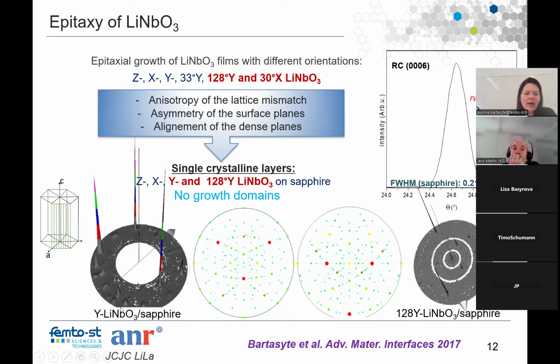So for example, if you look at Y-axis oriented lithium niobate, it's very asymmetric. If you look at the dense planes, here we have a stereographic projection. So we have 0, 1, 2 planes, which are very asymmetric, and you see that we get those three planes as expected. So it means that we don't have any growth domain. We have a single in-plane orientation. The same here, another example of Y128 orientation, as expected.